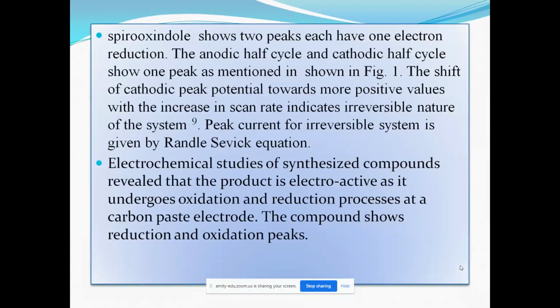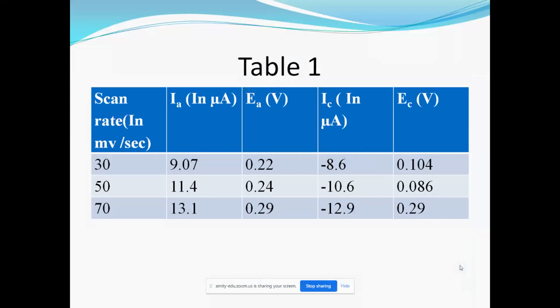The spirooxindole derivative shows two peaks, each with one electron reduction. The anodic half cycle and cathodic half cycle show one peak, as mentioned in the previous figure. The shift of the cathodic peak potential towards more positive values with increase in scan rate indicates the irreversibility of this reaction. Peak current of an irreversible system is given by the Randles-Sevcik equation. The electrochemical study of this compound revealed that the product is electroactive and undergoes oxidation and reduction processes at the carbon paste electrode. The various cathodic potential values, cathodic current values, anodic current values and anodic potential values are shown in this table at different scan rates.